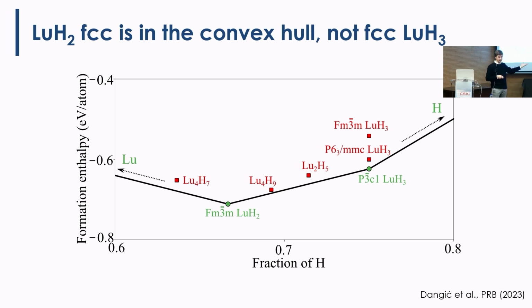This is also FCC, okay? But it's not in the convex hull, so it's not energetically favored. There are other LuH3 compounds, with a more distorted symmetry, that have lower enthalpy, okay? Anyway, as it was FCC in the experiment, we considered that maybe the parent structure was either LuH2 or this LuH3. So we analyzed them further.